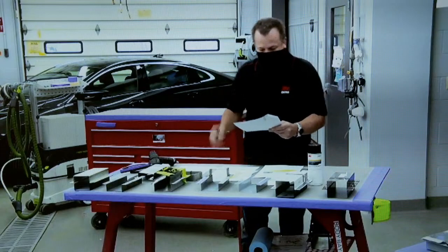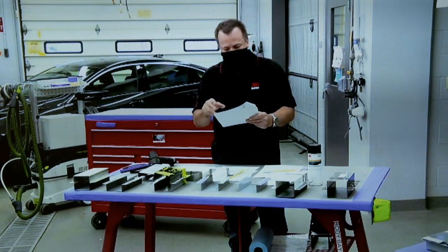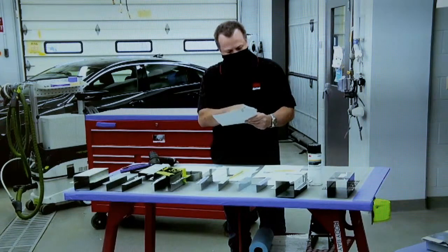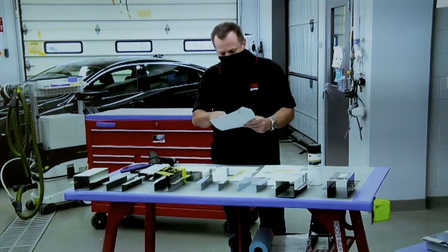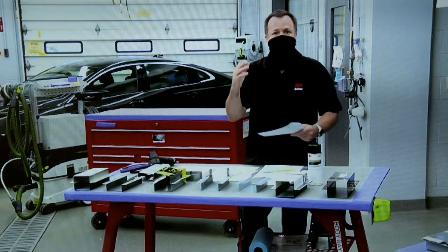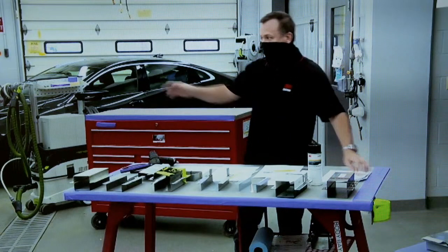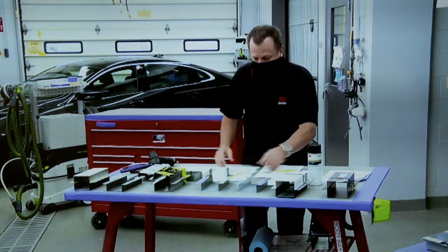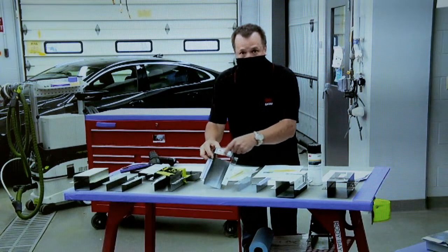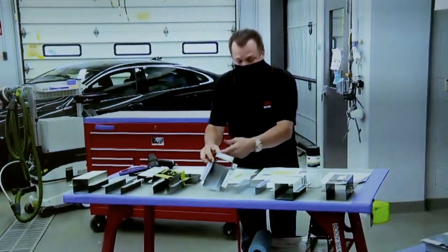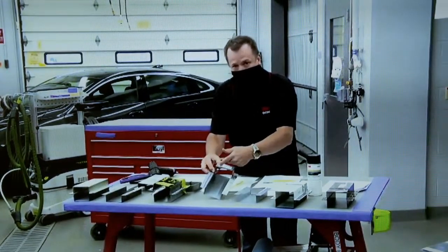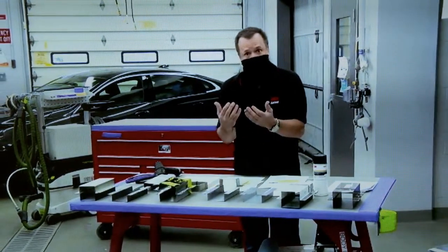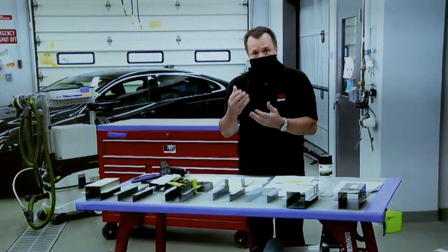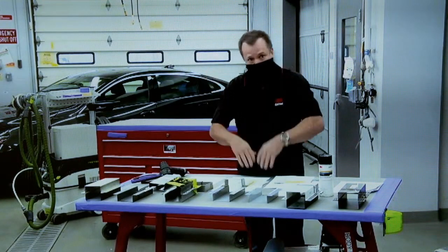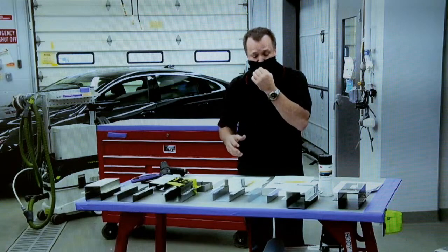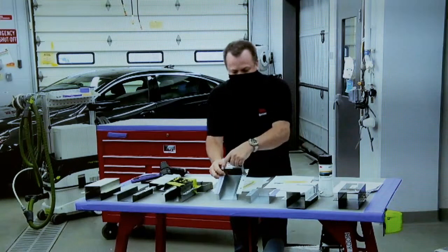The soot prevents satisfactory cavity protection. So what they're saying, and Ryan's going to address this, is if I don't clean the paint coatings from the sectioning area, or zinc or paint coatings, and I weld there, now I'm going to get soot on the inside. And when we cavity wax that, we're going to cavity wax right over the soot, which is going to later fall off or flake off. So they want the bare metal clean in the weld area.